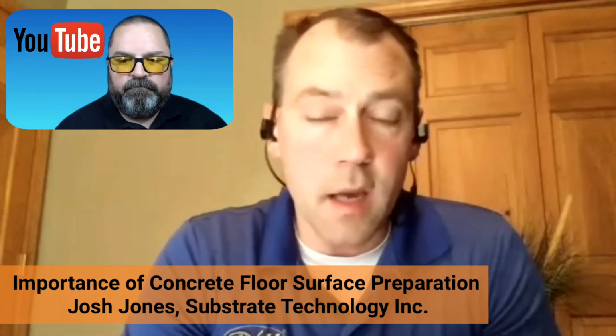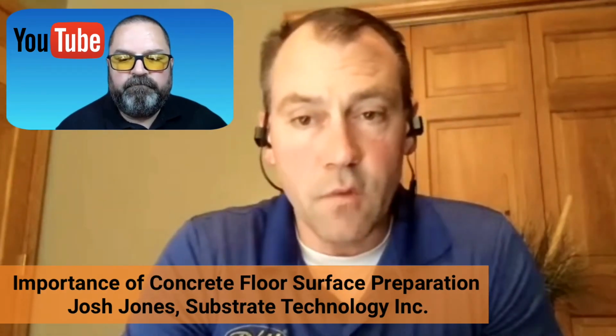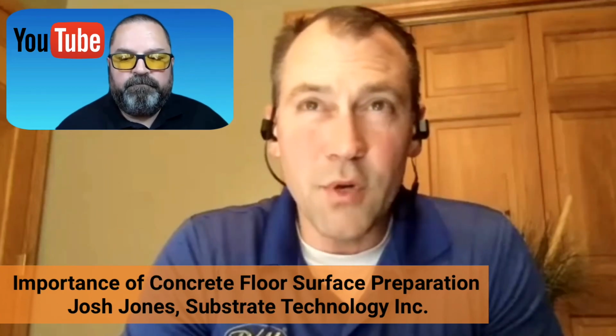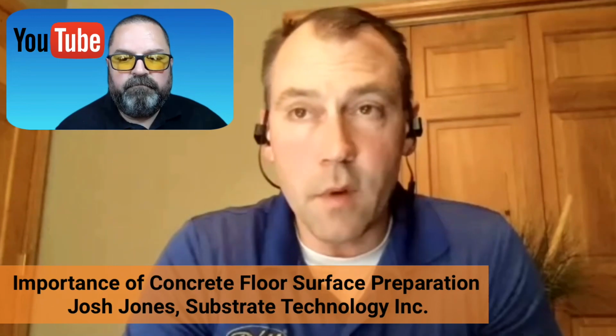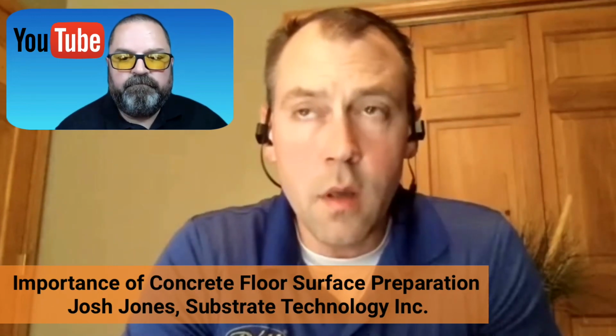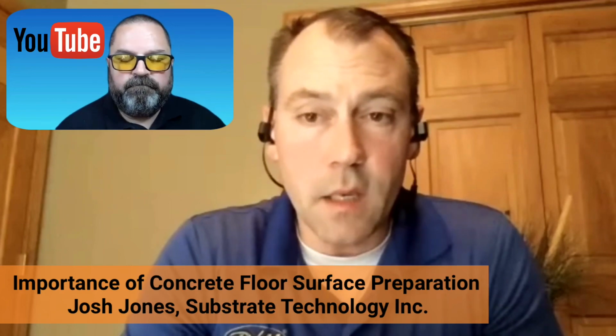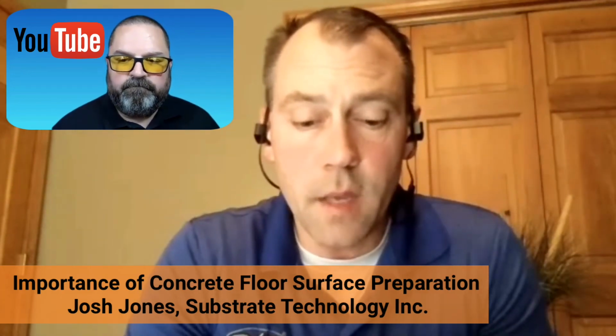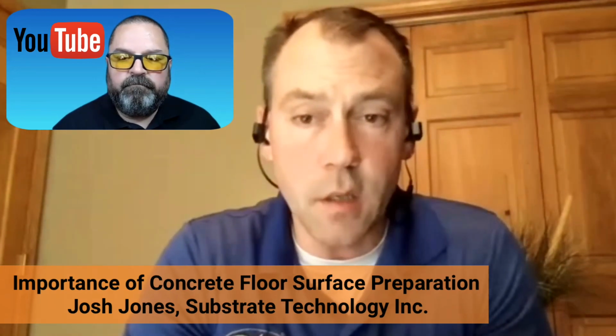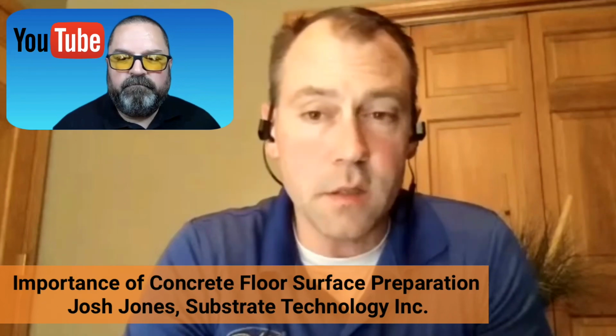They may call it a concrete surface profile of a 2, a shot blast, concrete surface profile of a 3. Bush hammer is kind of an obscure way to profile a floor, but that would be what they would call a concrete surface profile of 4. And then you have a scarifier, which is probably the most aggressive means to profile a surface, because it's literally hitting the top of the concrete and breaking away chunks. But some coatings require that for the sake of bonding or gripping to the surface.